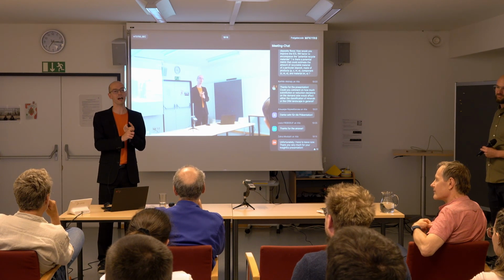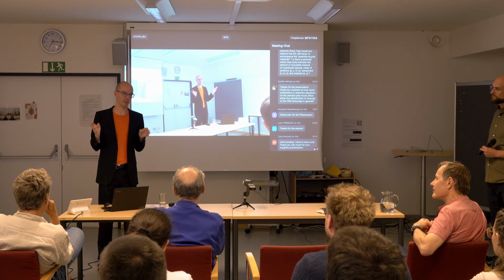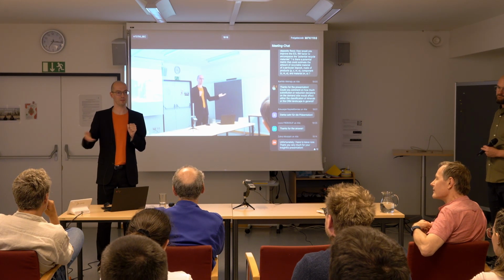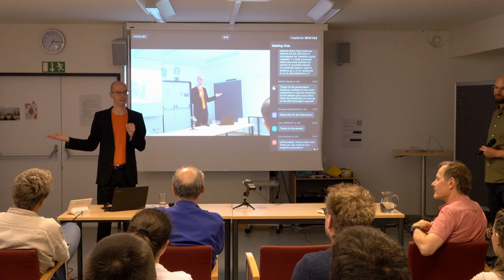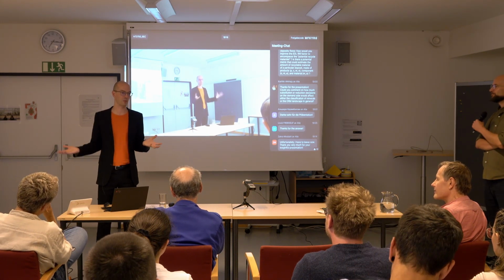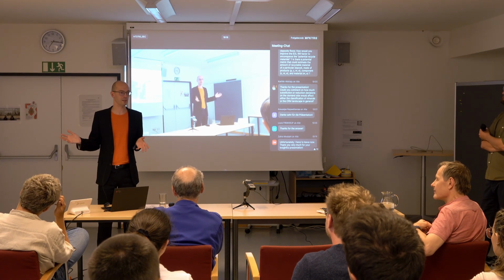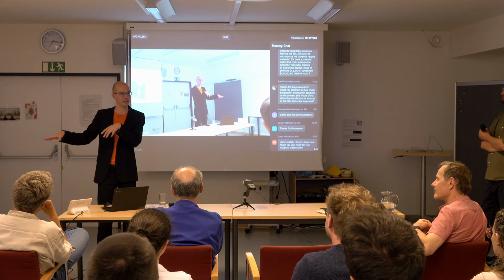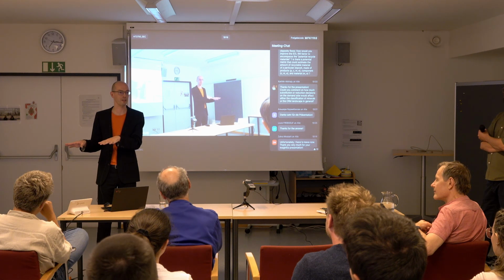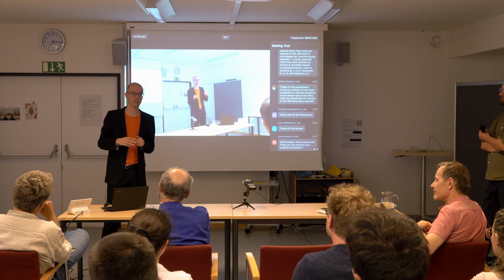So you do have gallium concentration, still in orders of ppm, in red mud, which is a byproduct waste material occurring during aluminum processing, very generally speaking. It's a waste material that needs to be dumped somewhere, so you will never touch this again, and you will not get gallium back from that. And it's into the environment. That's definitely a loss, and it's a huge loss in terms of gallium.